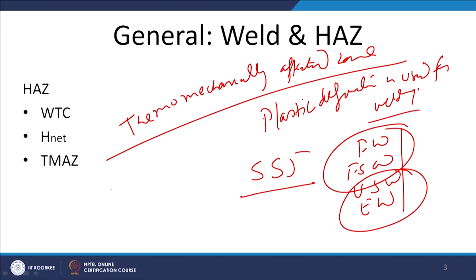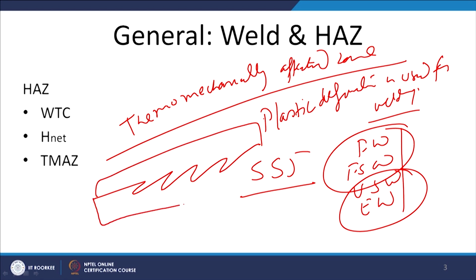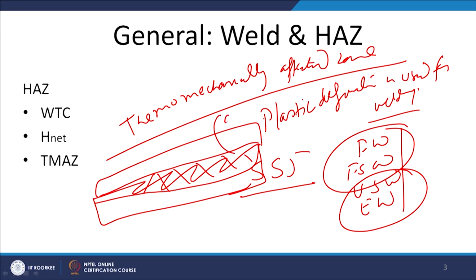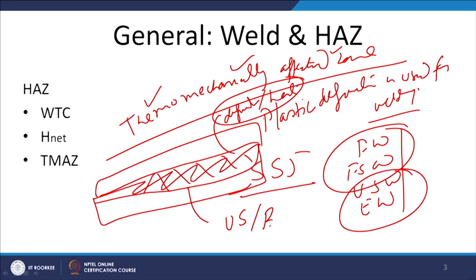So, whenever this kind of deformation occurs, we will notice that the interface is deformed like this. This kind of deformation at the interface will be leading to the formation of a zone which will be having the effect of deformation as well as heat, and that is why it is called thermomechanically affected zone. So, this is the typical characteristic of ultrasonic welding and explosive welding.